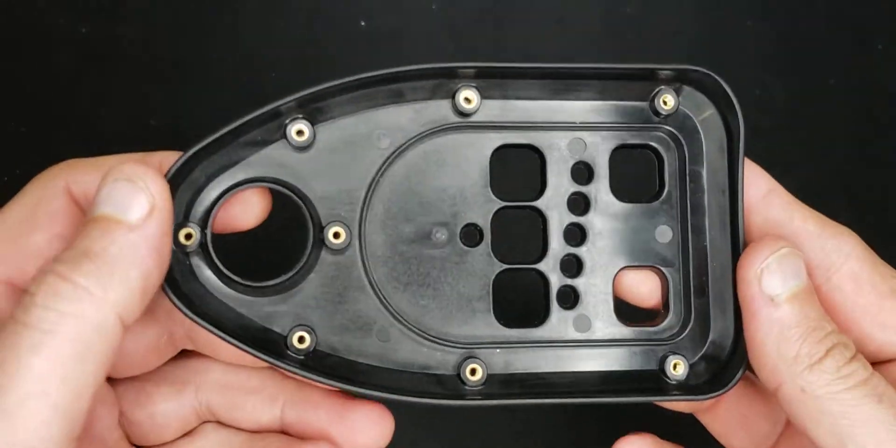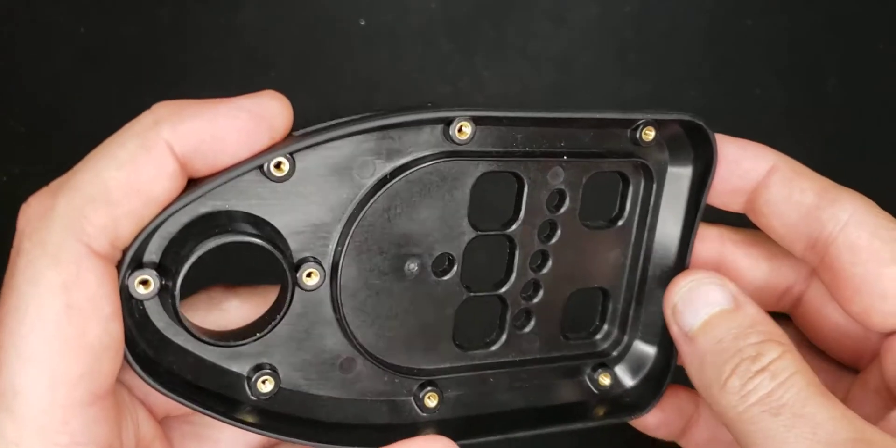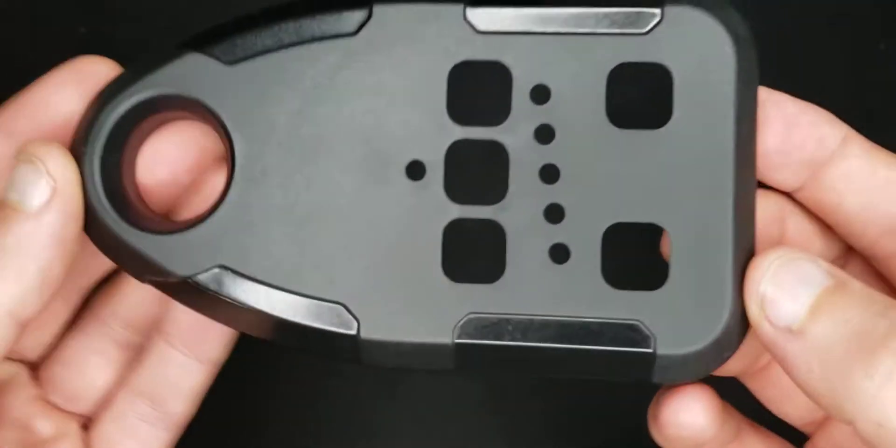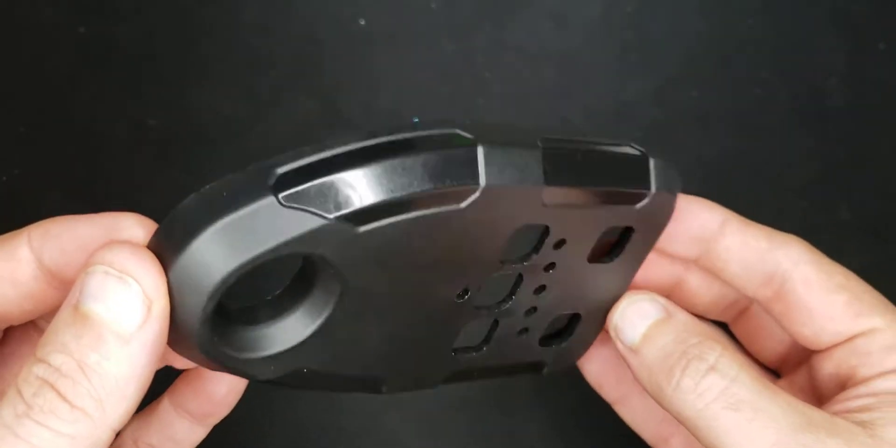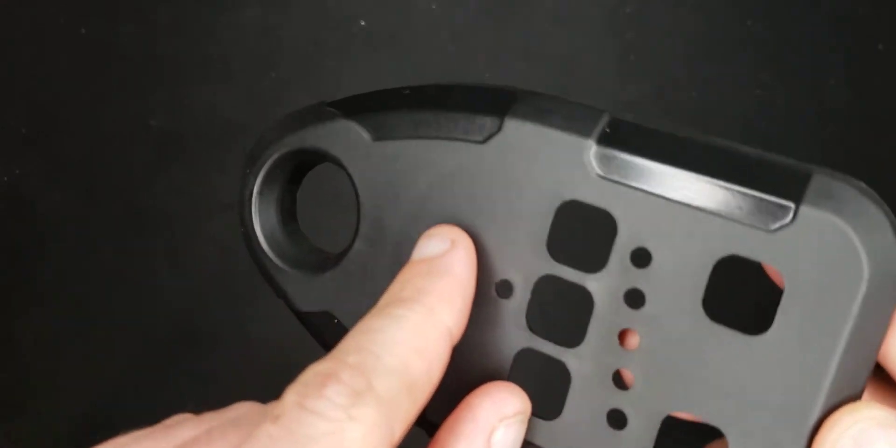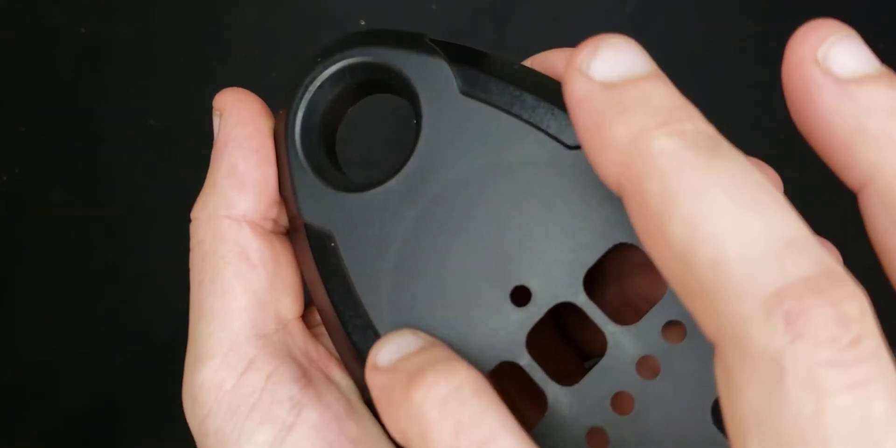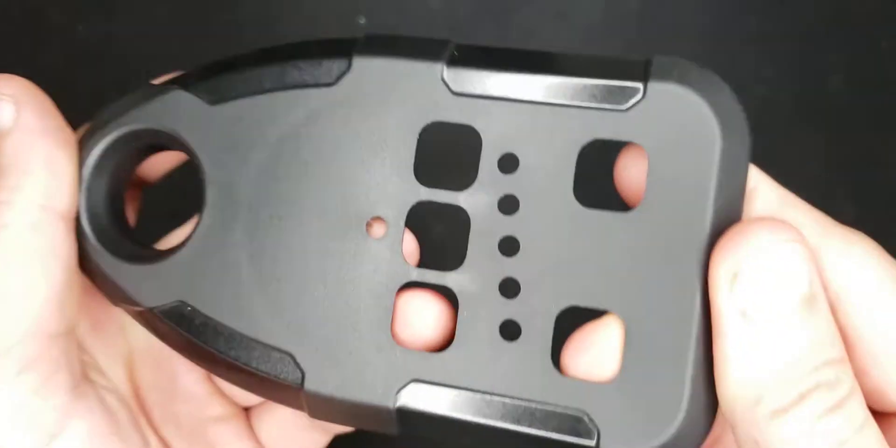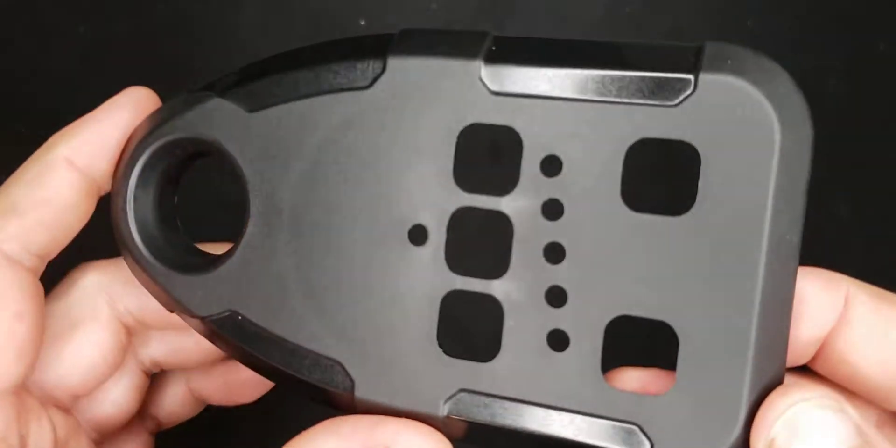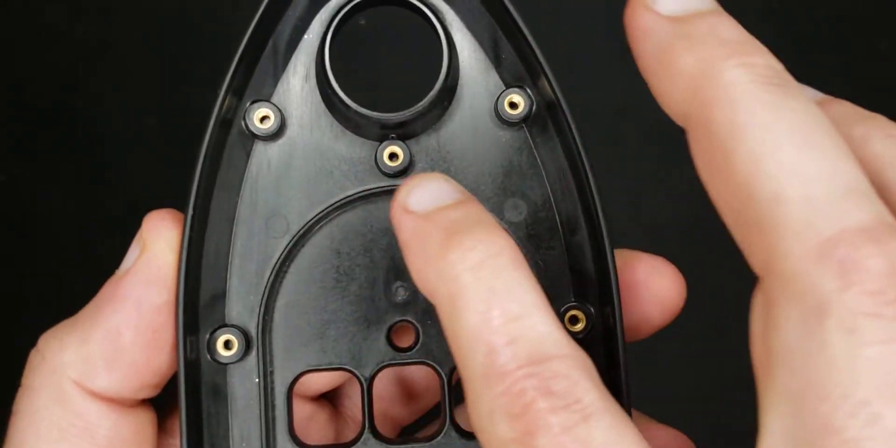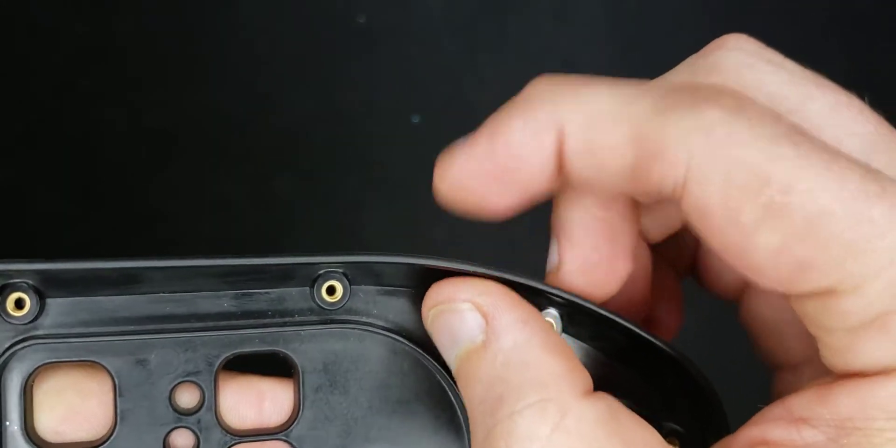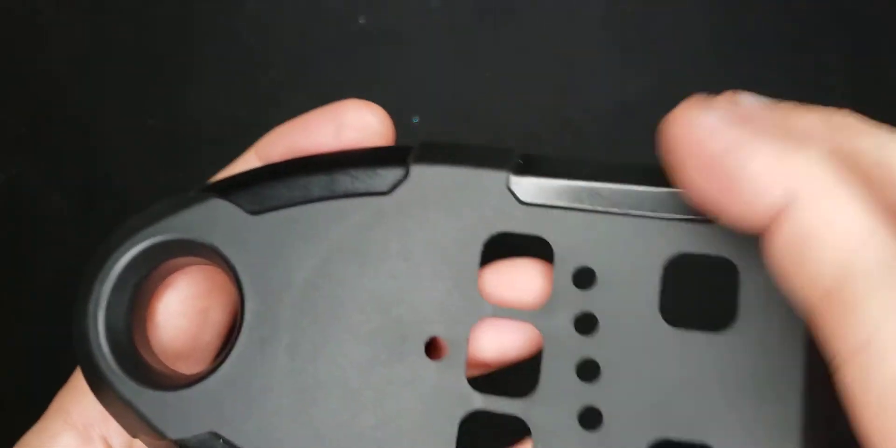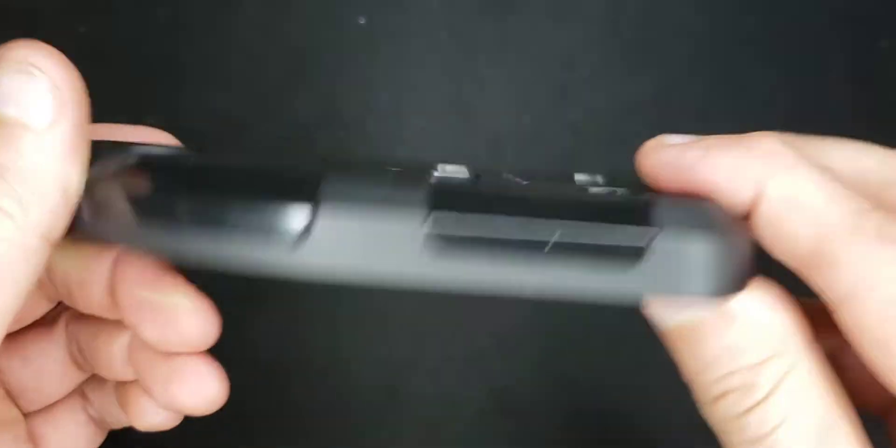You really only want to save reverse or A-side ejection for when you really need it. But when you do really need it, it can make wonderful parts like this that really have no evidence on the outside that it was made by injection molding. On this part, again, this is a sample run, not production parts yet. You can see a little bit of a sink from that rib that's on the underside, but really that's the only indication. And that'll be gone by the time that the injection molders get their processing more finely tuned. So you shouldn't be able to even see that, especially how thin it is. That's less than a 50% thickness rib over the uniform wall thickness. So there's no good reason why that should be visible from the outside if the injection molding processing parameters are dialed in correctly.